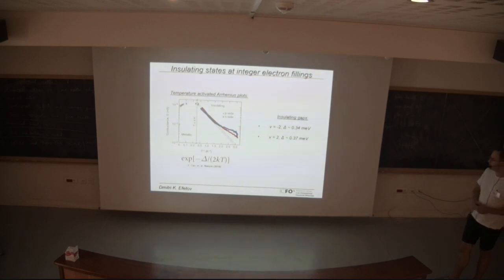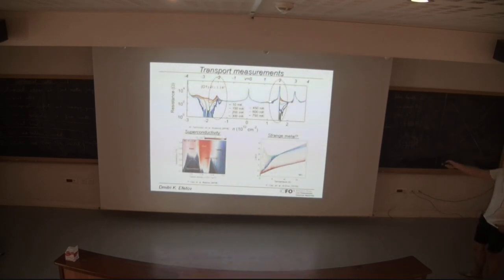Just for this expression here, we find that we can fit the temperature dependence in these states with this exponent here, and we typically find that the gap at filling factor -2 is on the order of 0.34 meV. The gap at filling factor +2 is on the order of 0.37 meV. So all of these gaps we can characterize pretty well with transport, and we can really show that, unlike expected from a single particle picture, these gaps are really sharply present. And that being said, if we tune the system slightly left and right from this integer filling, as I showed here, the system recovers normal metallic behavior, and there are no gaps, no weird interaction effects happening there.